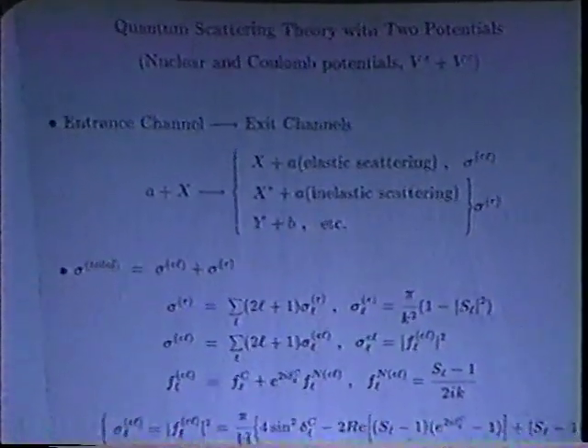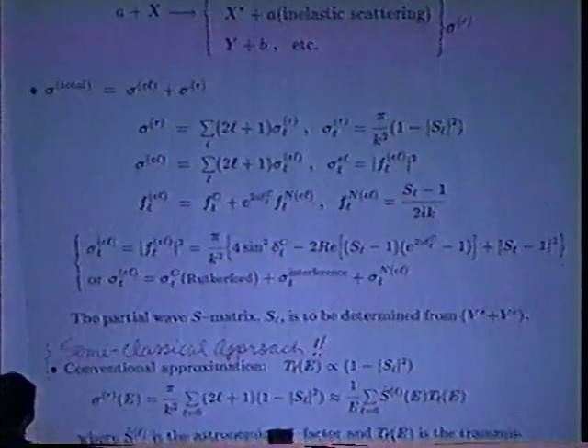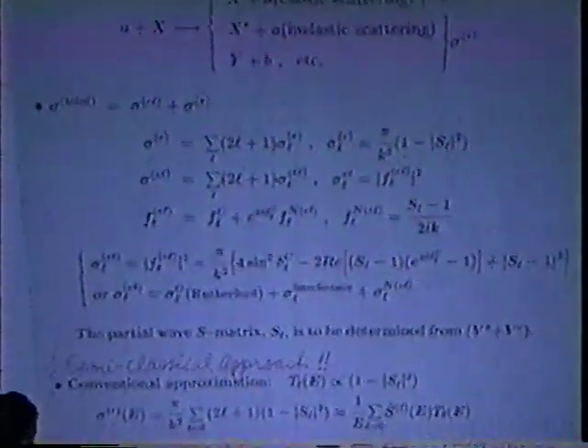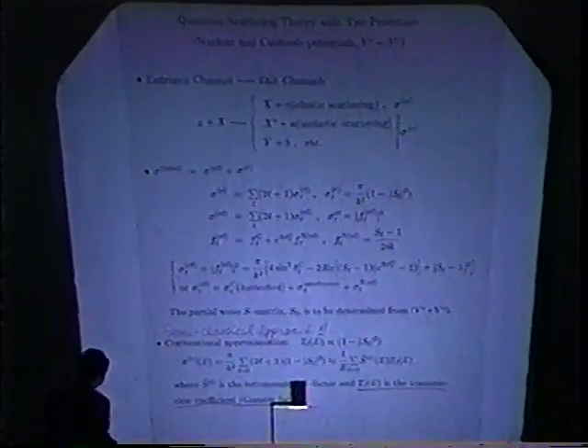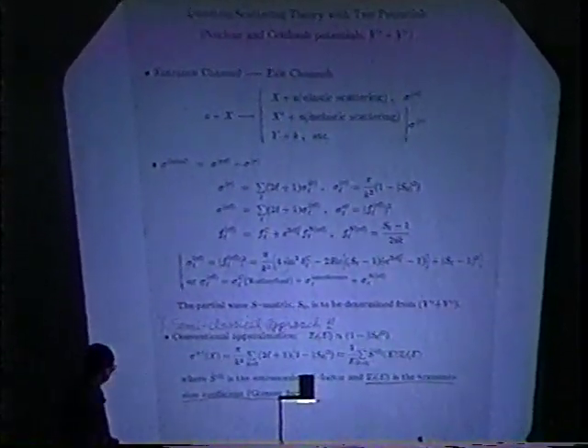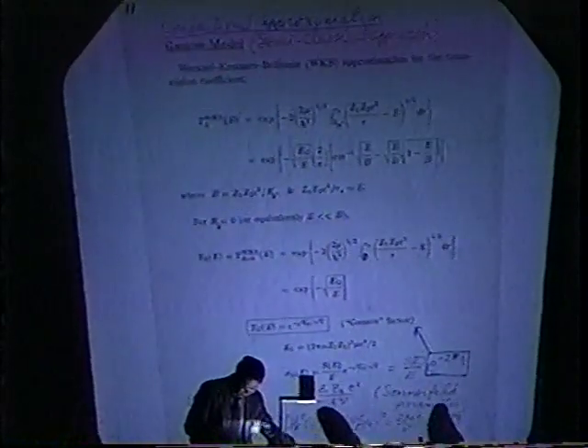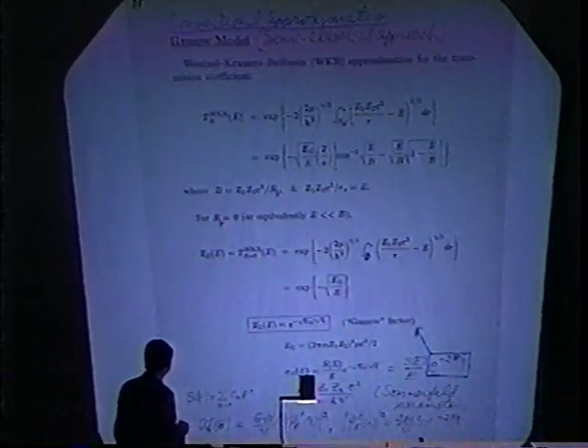We have two potential problems for, let's say, DD or nuclear reaction. And this is the standard way to describe two-potential quantum scattering theory in terms of S matrices and phase shifts. Now, the semi-classical approach has been used in the past. That's the conventional approach. You take this formula, but you substitute this thing with a transmission coefficient. And the way the transmission coefficient is obtained is to do the WKB approximation and get a simple integral, and eventually you end up with the famous Gamow.